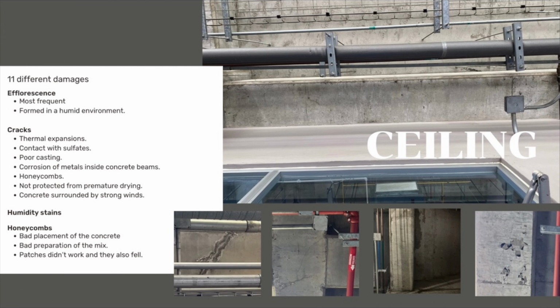It is formed when the construction is in a humid environment, causing the salts to travel through the porous material until they reach the surface and crystallize, leaving a white powdery residue. Cracks are another of the most frequent problems along the ceiling and can have different causes, such as thermal expansions, contact with sulfates, poor casting, corrosion of metals inside concrete beams, honeycombs, not adequate protection from premature drying, and concrete surrounded by strong winds.